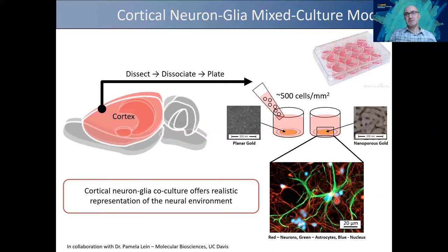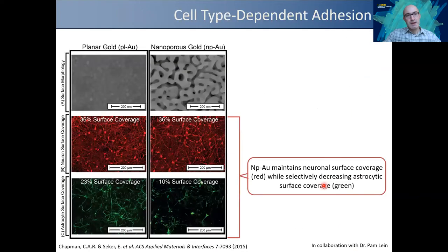And basically once you have these images, you can process them for cell counts and cellular spread. So basically how much the cell is covering the surface. So this is just an image that's covering it. You have the planar surface and the nanoporous gold surface. We've seen no difference in the neuronal coverage on either surface, which is good because we don't want the neuronal attachment to decrease. But we've seen, surprisingly, astrocytes were less likely to spread on these surfaces. So this is exciting because this is in support of the hypothesis that the topography is reducing the astrocyte spreading.